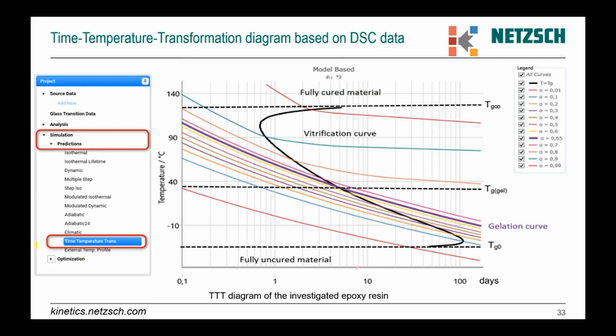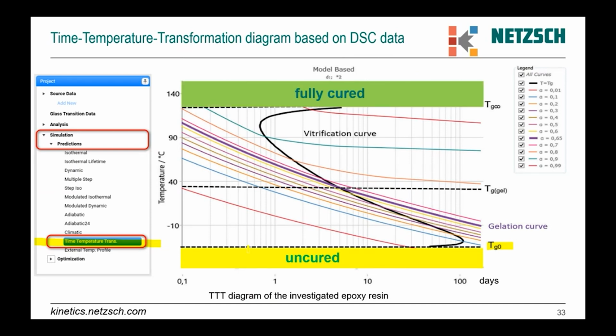Here in the software, we just select this diagram for simulation, and we have several parts. The first part is the glass transition for uncured material. Below this temperature, we have totally uncured material. Here we have the glass transition temperature for totally cured material. Above this temperature, we always have totally cured material. Then we have the gelation curve. This one, the violet curve here, means the gelation point.